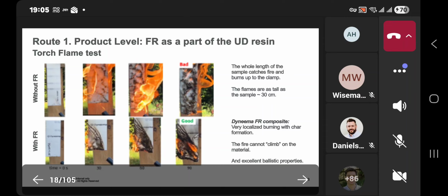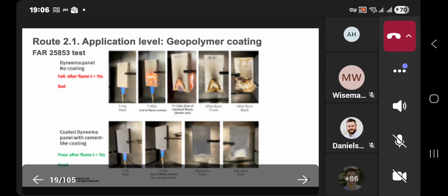In contrast, with a flame retardant, in the bottom pictures, there is some burning of the material, but it's very localized, and every single sheet of this panel forms a char, which helps to reduce the heat release and helps the material to eventually self-extinguish. And a bonus in this case is that the ballistic properties of these panels are retained. Next slide.